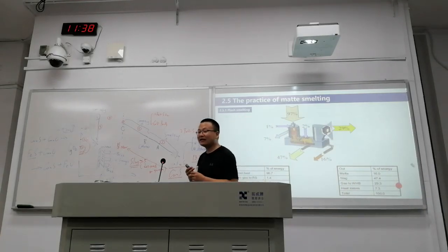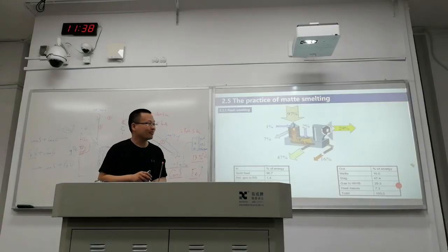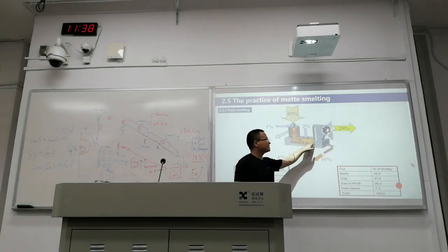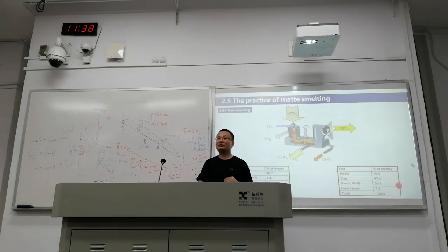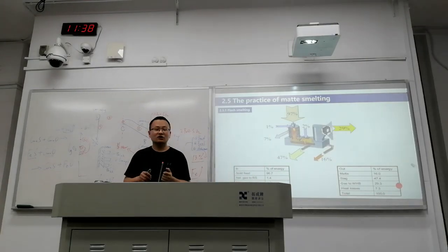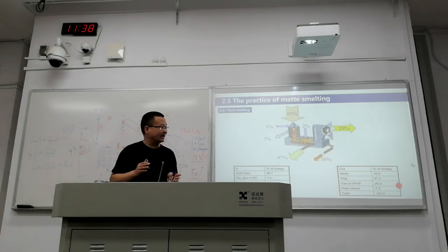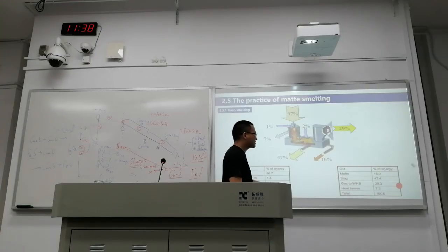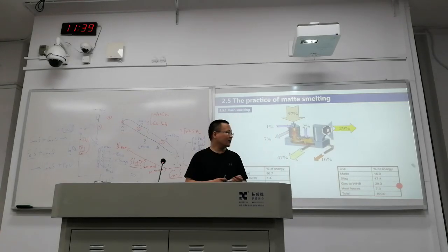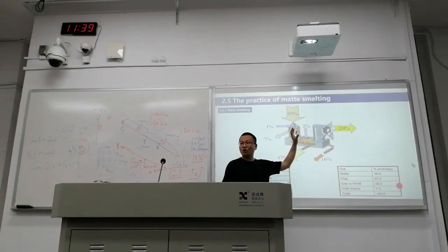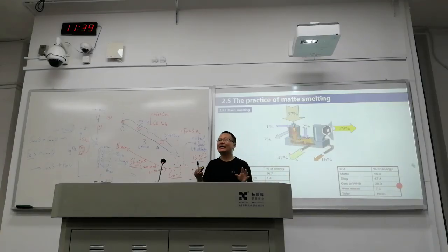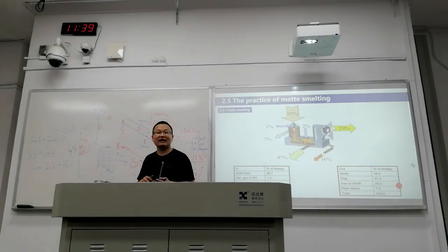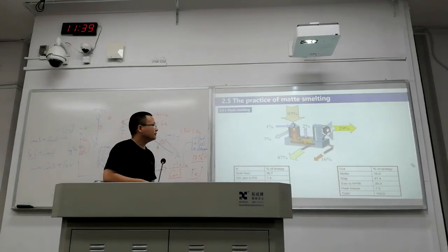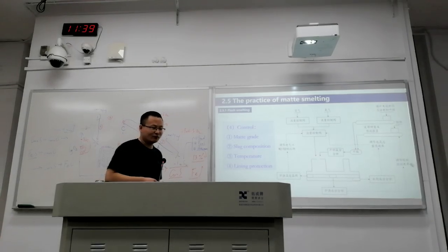Another is that when they are using pure oxygen, the arsenic will go more to the slag phase. We have been discussing the arsenic behavior last week. So when we are having pure oxygen, like 60% of arsenic will go to the slag phase. It's going to be another benefit. But when you are using pure oxygen, the reaction here will be more intense. So the challenges for the burner will be very, very different. So we should have other technical problems. Okay, so this is where we will end.